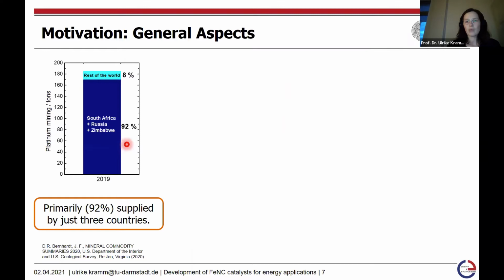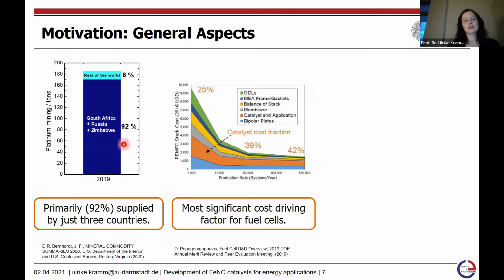Moreover, when we go to the costs of a fuel cell stack system, then we can see, so this orange range here is related to the catalyst cost fraction. We can see that almost independent of the production rate of fuel cell stacks, the catalyst cost fraction is the most dominant factor here. This is because the main cost of the catalyst within a fuel cell system is related to just the pure elemental costs of the platinum by itself.